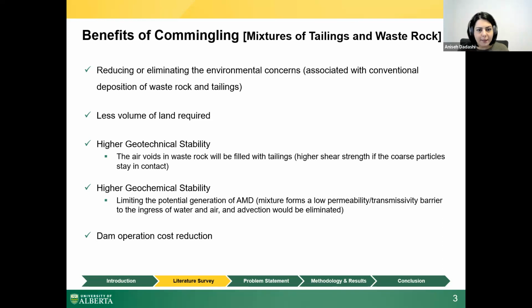Also, for chemical stability, the voids in the mixture provide a tortuous path for air and water under gravity flow, and oxygen transport by advection would be eliminated for this mixture. And the only oxygen supply would be oxygen diffusion. In addition, this material can be deposited in a dry stack, so we can reduce the cost of building and maintenance of tailings dams.